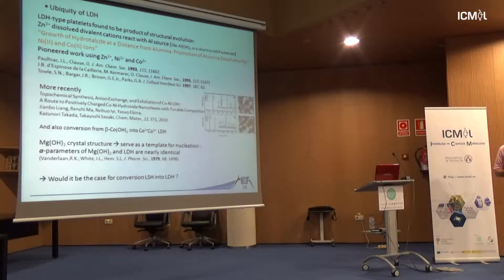If you want to trap lithium, in the case of different waste companies using lithium, you can add aluminum at a certain pH and you trap it to form lithium aluminium LDH. And more recently, it has been performed by the group of Professor Sasaki in Japan, and they were doing some cobalt nickel tunable composition directly from cobalt or from nickel hydroxide, as well as a conversion of cobalt from beta cobalt dihydroxide.